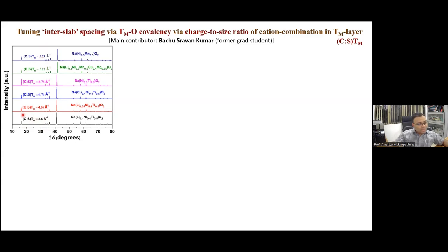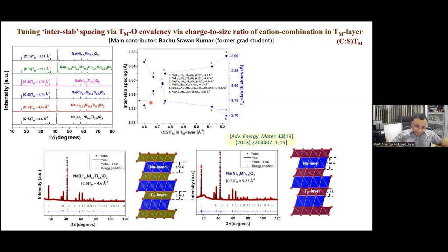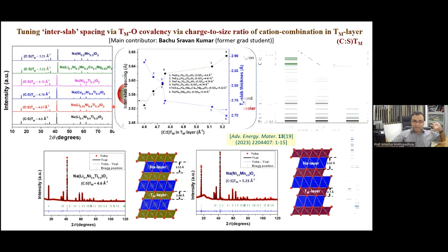So now, if the charge to size ratio is lower, we expect the transition metal oxygen bond to be less covalent or more ionic, and so we expect that the interslab spacing will be lower because the sodium oxygen bond will be stronger. Because the transition metal oxygen bond is less covalent, the effective negative charge on the oxygen ion is more, so the sodium oxygen bond will be stronger, and hence the interslab spacing will be shorter. And as the charge to size ratio gets increased systematically across our model compounds, the interslab spacing gets increased, and that is verified by our experimental results based on the materials that were prepared.